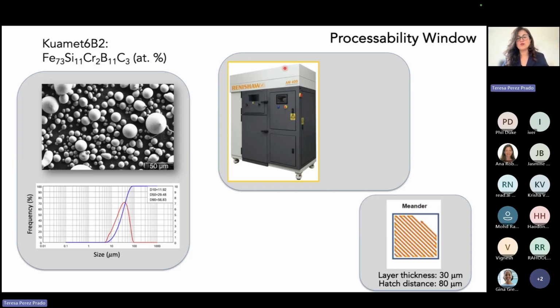We use this machine. This is one of the 2 LPBF machines that we have available at IMDEA Materials. It's a Renishaw pulse laser machine. It has 1 laser in this case. And like I said, we first tried to fix some processing parameters, so a simple scanning strategy, this meander scanning strategy. We fixed a layer thickness of 30 microns. This is also standard, and a hatch distance. So this is the distance between 2 consecutive scan tracks of 80 microns. This is also very standard.